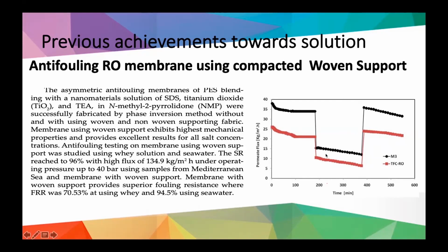And here we have seen clearly the membrane in red, which is the TFC membrane, the commercial one, when compared to our membrane, M3, which is the woven supported prepared RO membrane in presence of titanium dioxide. Here you can see the effect of the presence of a supporting material, with a great enhancement in the flux to reach around 134.9 kilogram per meter square hour.